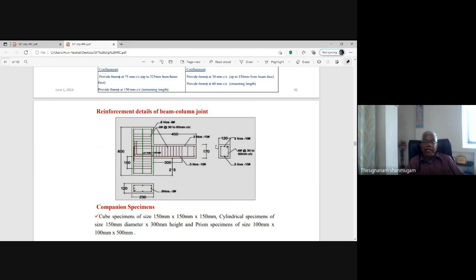120 by 170 is the size of the beam. It consists of 3 numbers of 10 mm diameter bars at both top and bottom, because of the reversible nature of the cyclic load. So both the tension reinforcement and compression reinforcement are the same, with 6 mm diameter stirrups at 30 mm to 60 mm centers. Here 60 mm centers, here 30 mm centers up to a depth of 2D. Similarly, up to a depth of 2D the ties are placed at closer intervals, and beyond that the ties are placed at longer intervals. The reinforcement in the column, 120 by 230 mm size, is 8 numbers of 8 mm diameter bars provided as longitudinal reinforcement, and 6 mm diameter ties at 30 mm and 60 mm centers.